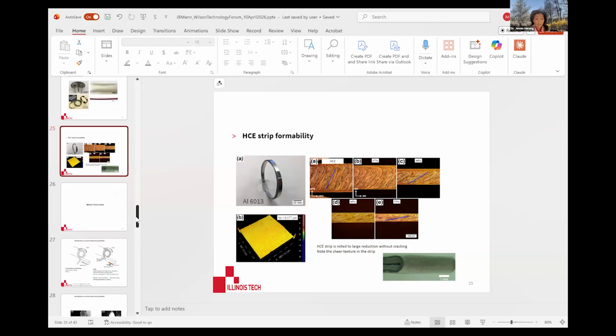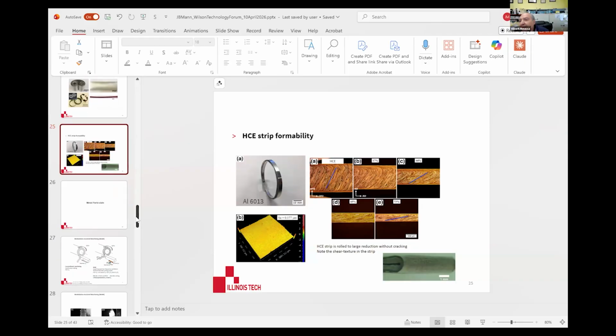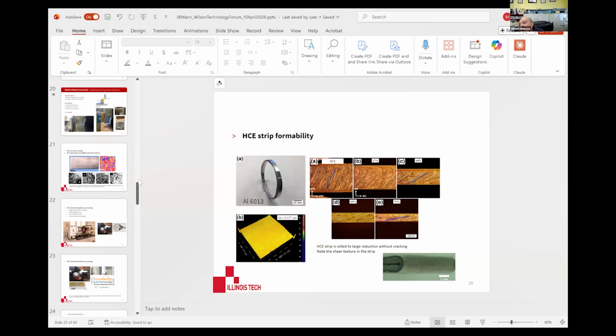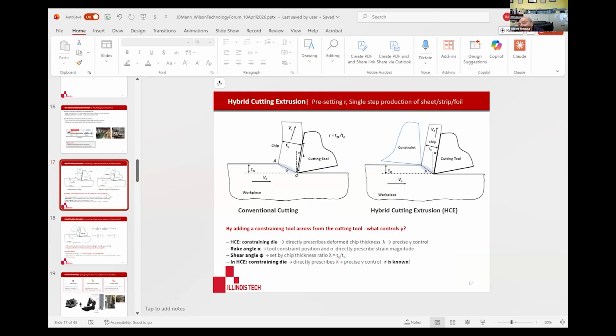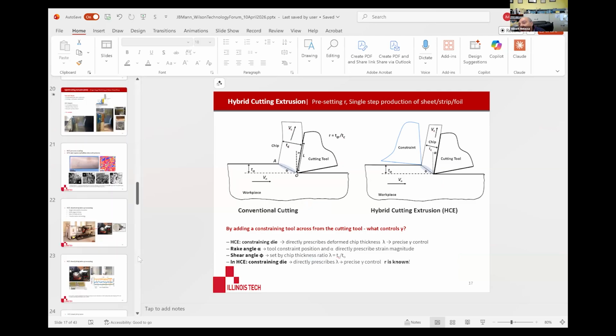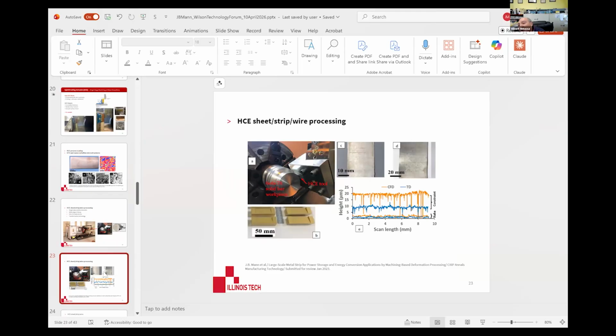Okay, thank you, Albert. Jim, very nice. And I'm glad you emphasized the importance of that constraint, because without it, the other side of that strip didn't look too good in your pictures. And I presume it's because the stress wave reflects off an open surface, so you get a rarefaction wave, and that's really ruining the structure of the backside that is not constrained.